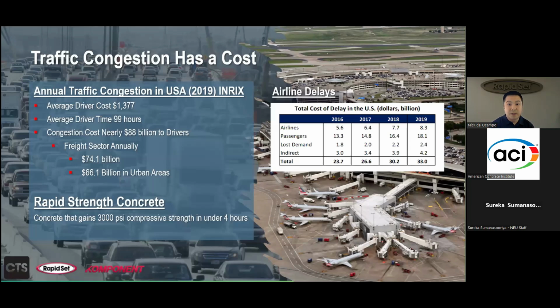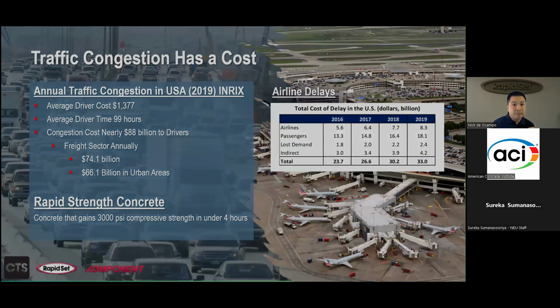And this is where CSA cement and rapid set cement can come into play. With concrete that can reach 3,000 psi in under 4 hours, the length of closures can be reduced, which can alleviate large portions of this congestion that typically occur during rush hour and daytime hours. So if you can transition a closure from a weekend closure to a 24-hour closure, or a 24-hour closure to an overnight closure, you can drastically reduce the impact of traffic congestion to the commuting public, which will reduce the financial costs and emissions associated with idling and diverting traffic.